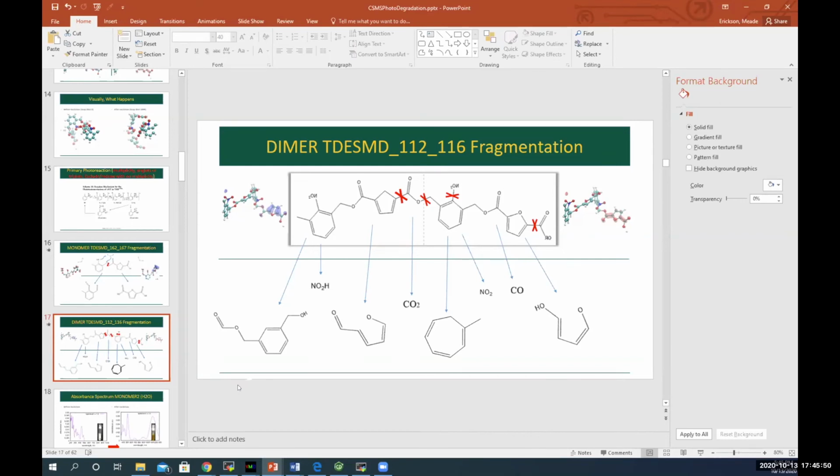So in this diagram, it looks like the reaction that you were modeling went too far, which would correspond either to a real experiment focusing a very high intensity laser that is about to burn the polymer, or we expose it to regular light, but for a very long time. So it decomposes into too many fragments. Instead, in a real experiment, if it is not our goal to burn the polymer, we can just irradiate it for a shorter time or with lower intensity.